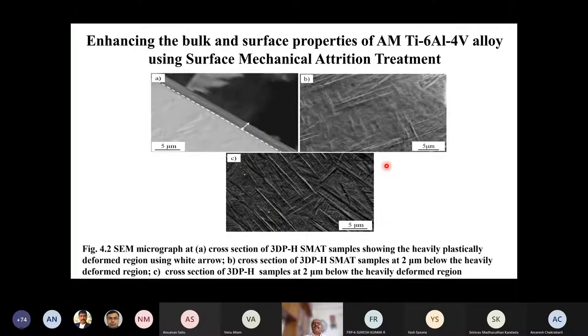Another post-processing thing that we have done, mind it, we have not done any HIPing because we didn't have access to HIP. And we always felt that HIPing is not the best way to tailor things, because HIPing just closes porosity, and the process takes place at a very high temperature. At those high temperatures, we get more damage to the optimized microstructure than the benefit that we get by reducing certain fractions of porosity. So we followed different methods.